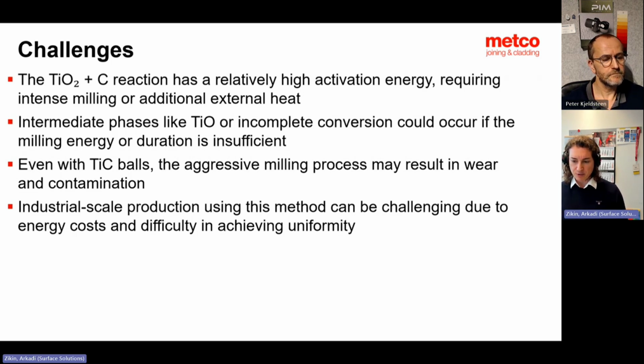But the main obstacle at that time, and unfortunately probably remains for this method, is industrial scale up. So if somebody comes and says, I need 100 kg of titanium carbide, probably this would be a very nice method. But if somebody says, okay, we have an application where we need 100 tons of powder produced this way, this technology unfortunately failed to reach industrialization. And that's why it's not really widely used for high volume powder production.